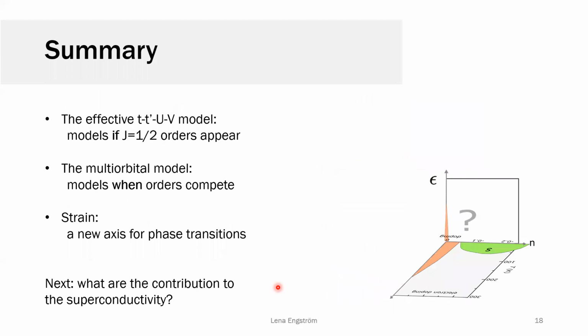To summarize what I've done with this problem and what the idea is: we have this effective model, which is the one that predicts superconductivity, but it's only relevant for part of the iridate model and only under some strict assumptions. However, I've been considering the full multi-orbital model to characterize which of these orders dominate and how we can change them. And then I've specifically been looking at some experimental effects that can have a large impact on which different components change when we increase it.